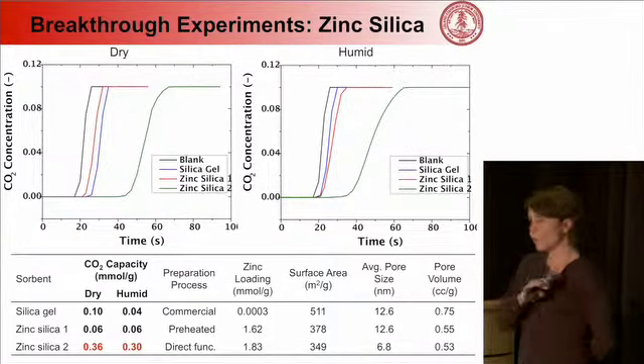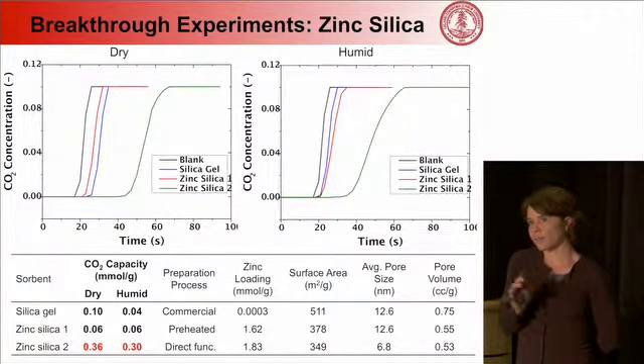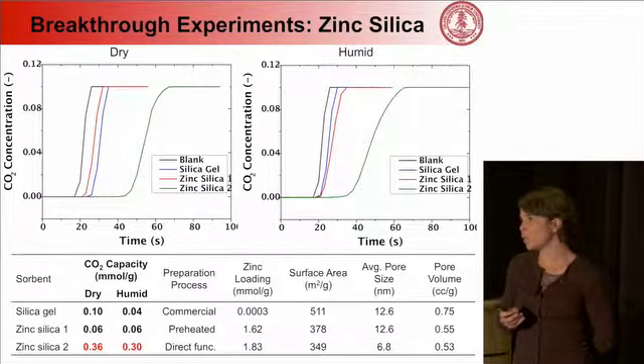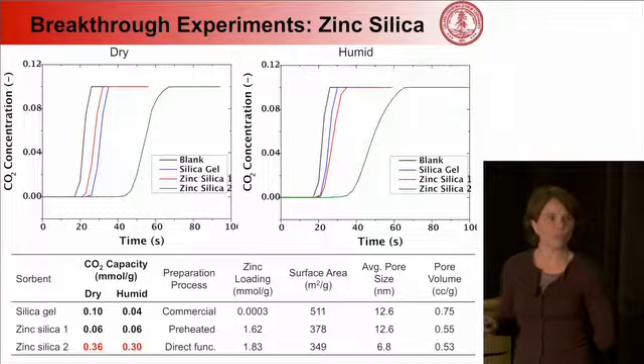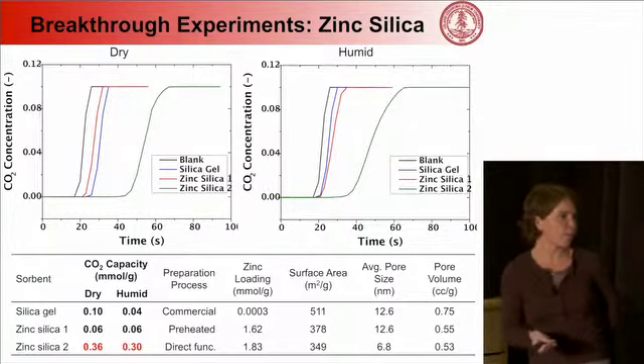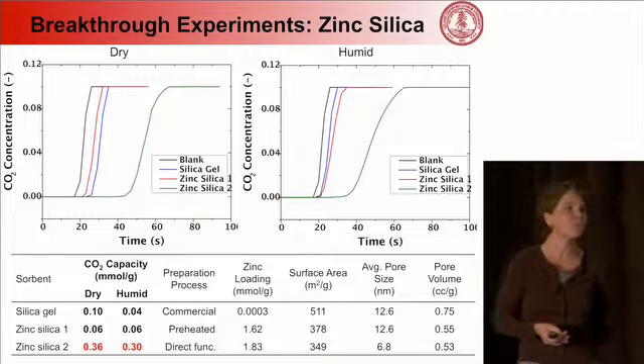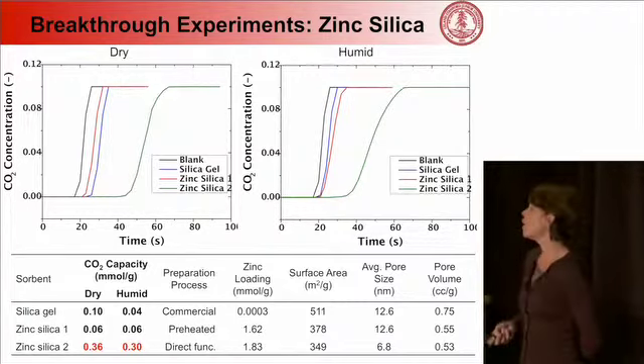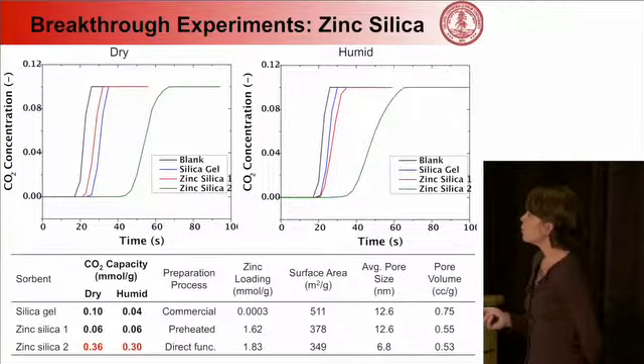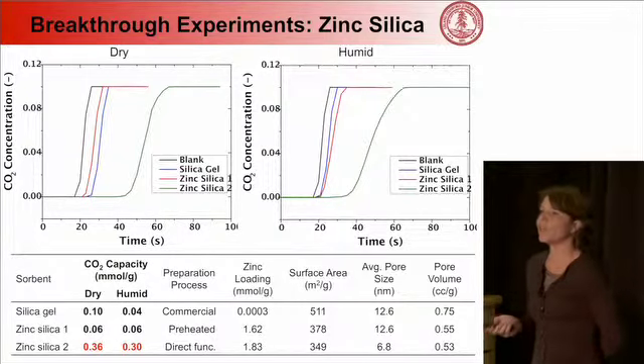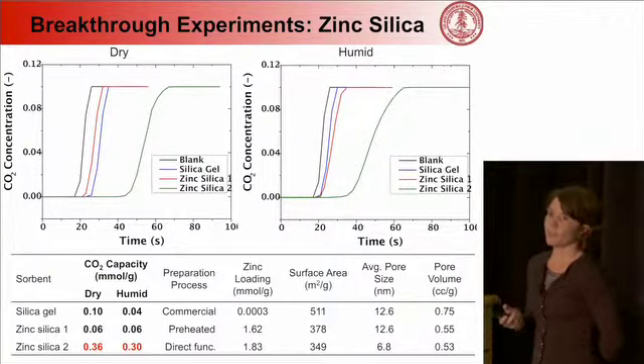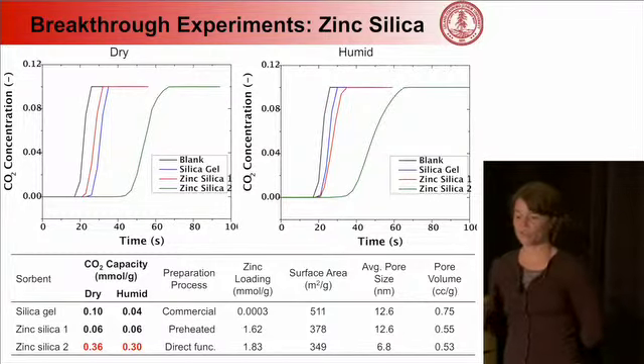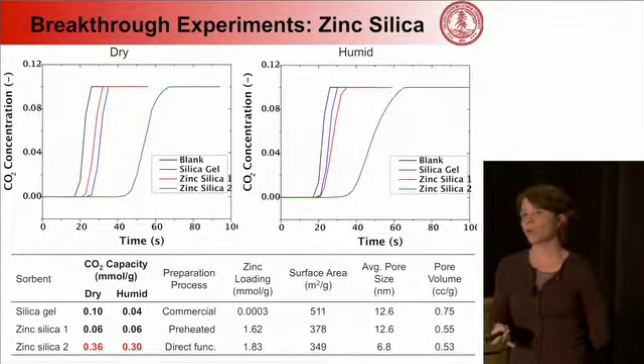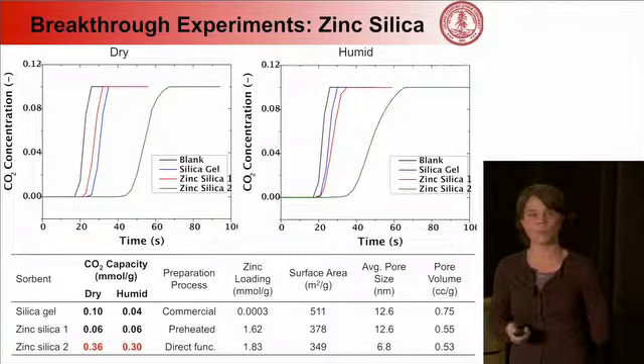And as you saw with the other materials before, going as high as, say, 1.4 millimoles per gram at 0.1 bar of CO2, it's true that the loading of CO2 is not promising on these materials. So as is, the capacity is not a winner for these materials. But what we found exciting was the fact that the CO2 capacity didn't change in the presence of water. So we're getting a sorbent that is selective to CO2 over both water and nitrogen, which is a promising result.